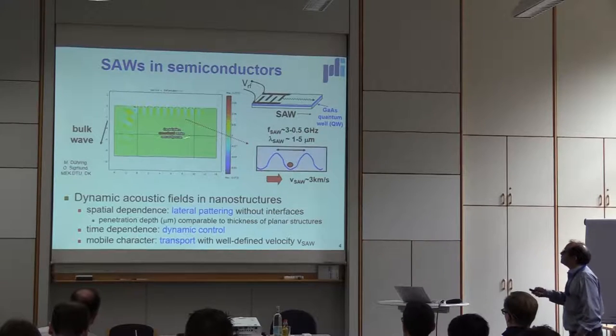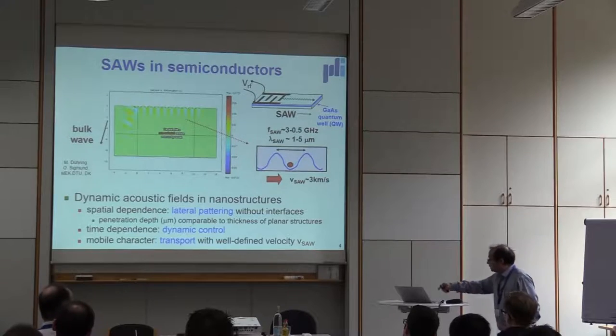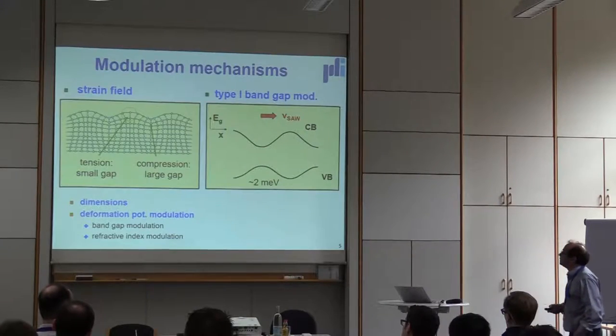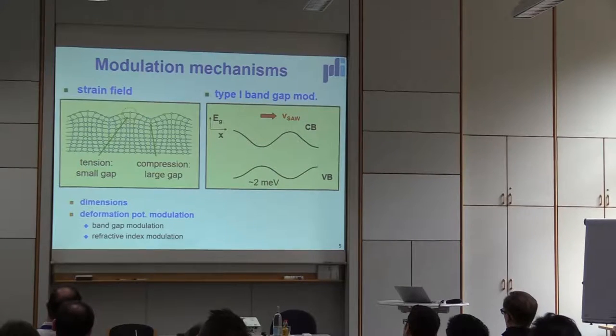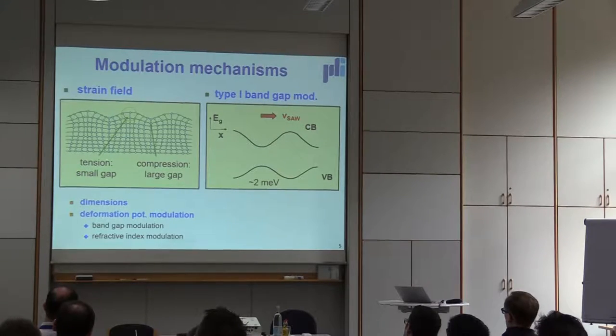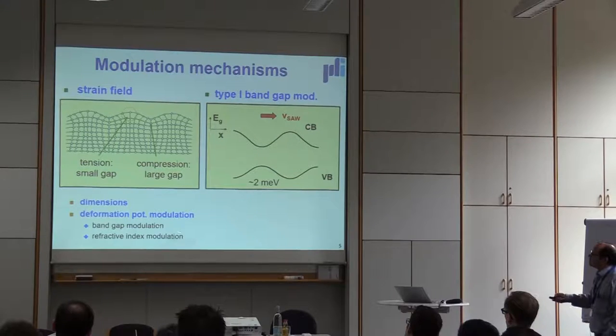To understand how these vibrations interact with the material, the interaction mechanisms are quite simple. This is a picture of the atomic displacements created by a Rayleigh acoustic wave. The wave deforms the material with its wavelength, changing dimensions and locally changing the density. Changes in density or symmetry lead to modulations of the band gap — this is the deformation potential mechanism. If you change the band gap, you change many other properties, for instance the refractive index.